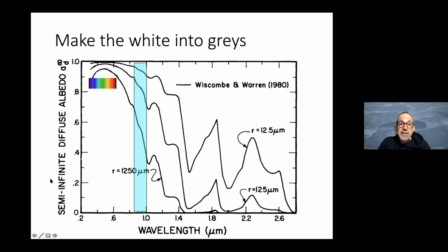What we have here on the y-axis is the albedo. We see that in the visible light, the albedo is very high. That's why for us, snow is white. When we look at the near infrared, we see that depending on the structural size, on this optically equivalent diameter, small particles have a higher albedo, a higher reflectance, than coarser structures.